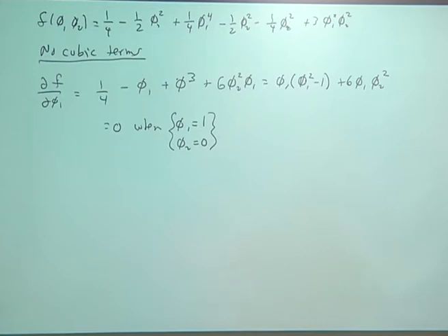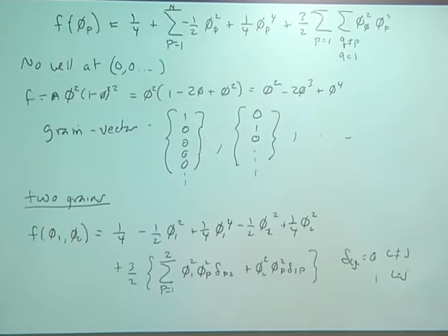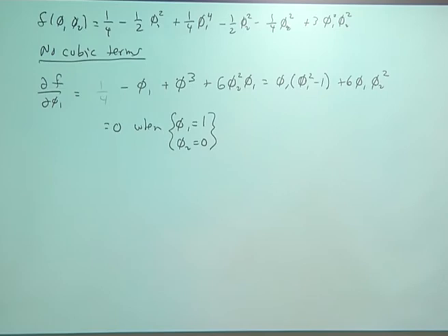Okay? And so that's what I meant by there's a well at each one of these order parameters. A well for each one of these vectors here. So we have N order parameters, and so you have N evolution equations, N Allen-Cahn equations.